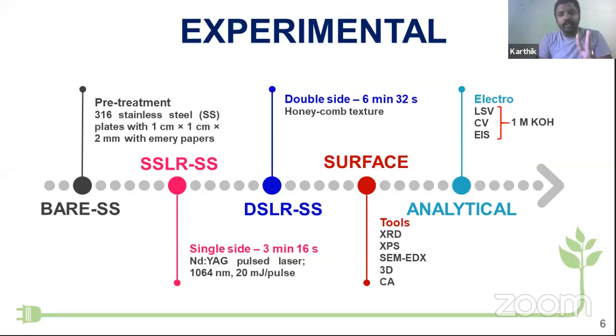So here we are using two kinds of substrates. One is single side irradiated and another one is both side, double side irradiated substrates. These substrates are subjected to surface analysis such as XRD, XPS, SEM, EDX, 3D, and contact angle. And further, it is evaluated for its electrocatalytic behavior through electroanalytical techniques such as LSV, CV, and EIS in 1 molar KOH solution.